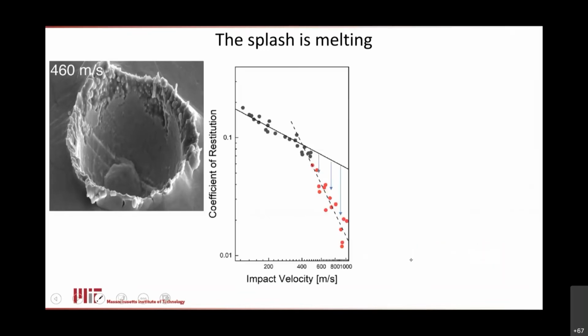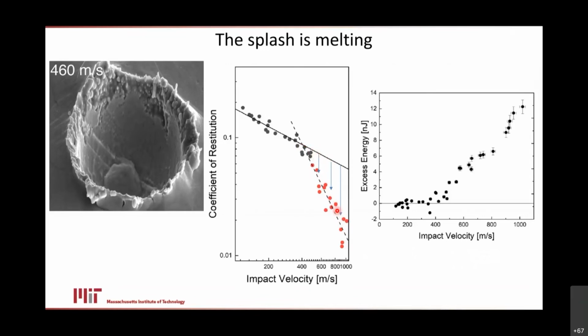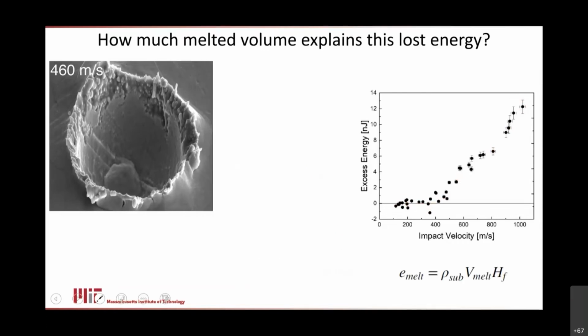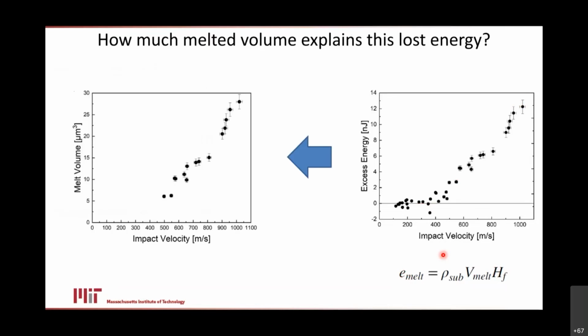All right, so let's now analyze this divergent behavior and try to measure a splash. So the first thing I might do is the same thing I did for copper. So I told you before that I've got a divergence from the power law. So there's excess energy being drawn out of the particle in this regime, and we can go ahead and quantify that. So here is the excess energy loss, which we are now attributing to the new physics that onsets once melting is present. In fact, if you want to be bold, you could say, hey, look, the only thing we know for sure that's new here is that there's melting going on. And so maybe all of this extra spent energy is due to melting. So you can do sort of an upper bound calculation, if you will, and you could say, look, every last bit of this energy is going into melting. It's going into the heat of fusion of tin. And if that were the case, then it's a simple linear conversion to figure out how much stuff melted. So here it is. Here's an upper bound guess.